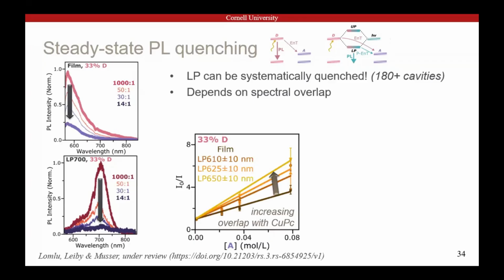If we look at the energy of the polariton mode, these are going to be plotted as Stern-Volmer analysis, where we're looking at the intensity of light emission relative to the unquenched case. A steeper slope means more efficient quenching. So as we increase the spectral overlap between polariton and acceptor, it gets quenched more. And that's what you would expect for a Förster process. It is maybe just getting absorbed by the quencher more because it's more resonant with it.